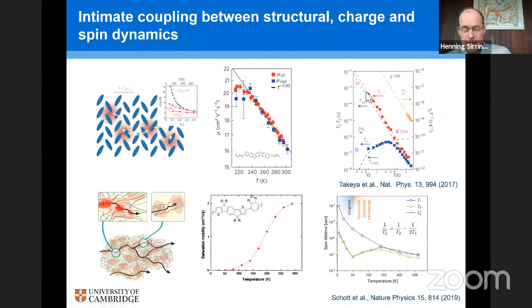And if you look at these plots here on the right-hand side, the top one is T1 and T2 for a highly crystalline molecular semiconductor. And it also shows this peak in T2 around 100 Kelvin. And that's very similar to what we've seen in the polymeric system. And so the reason for that, we think, is this close coupling between the structural dynamics driving these oscillations in the carrier wave function and that inducing spin relaxation. The mechanism for that seems to be very similar in molecular systems and in polymeric systems, and it allows us to understand a bit better how the physics of transport in these two systems is related.